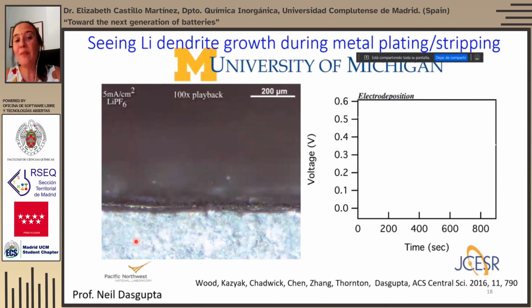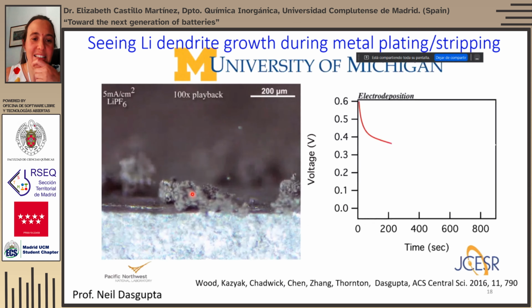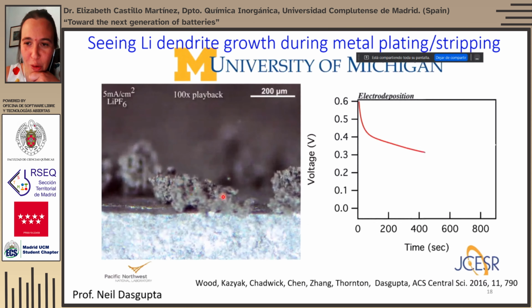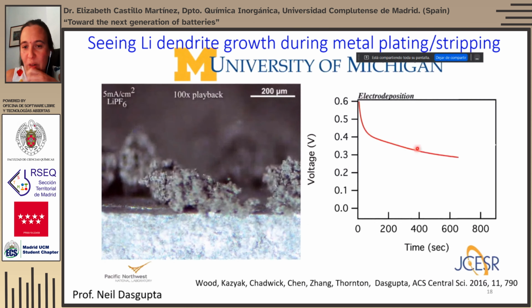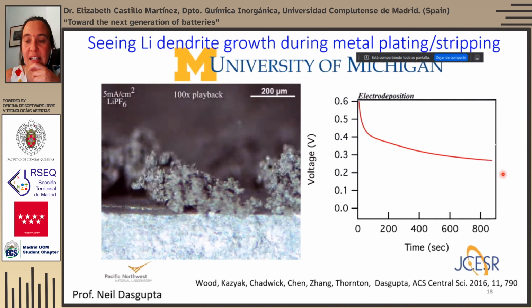Yeah, I'll move on. So what lithium does, instead of forming a homogeneous thin film, is grow in a very inhomogeneous way, forming dendrites. And these dendrites tend to grow towards the opposite electrode, and sometimes they cross the separator and reach a short-circuiting event. Oh, here it is. You can see the inhomogeneous growth while we are going down in voltage towards 0 volts versus lithium.